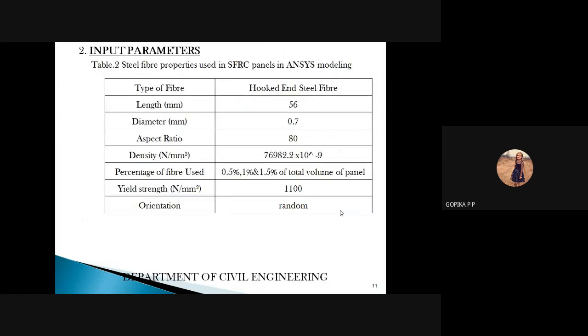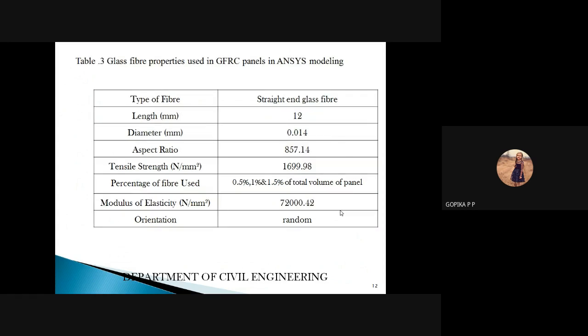Then next is input parameters. This table shows the steel fiber properties used in SFRC panels in ANSYS modeling. Type of fiber is hooked-end steel fiber. Length is 56 mm, then diameter is 0.7 mm. Then aspect ratio, the ratio of length to diameter, is 80. Density is 76,982.2 × 10⁻⁹ Newton per mm cube. Percentage of fiber used is 0.5, 1 and 1.5% of total volume of panel. Orientation is random.